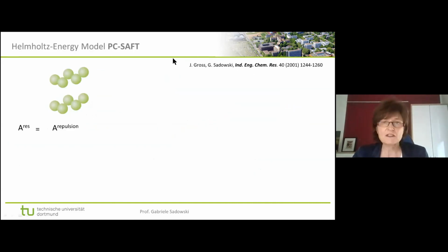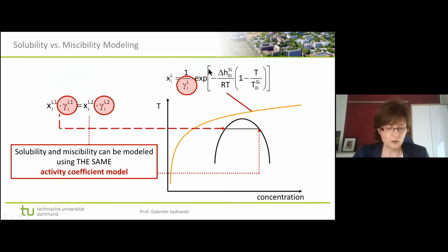Of course, what you see is that we need to know also the melting properties of the API, but they are usually available. And then we fit the pure component parameters of the API to the solubility data. And it turned out to work. So we then prove whether we can use the same parameters to calculate the solubility of the same API in different solvents. And once we believe that we have a parameter set that works not only in one solvent, but also in different ones, this is the one we go with.